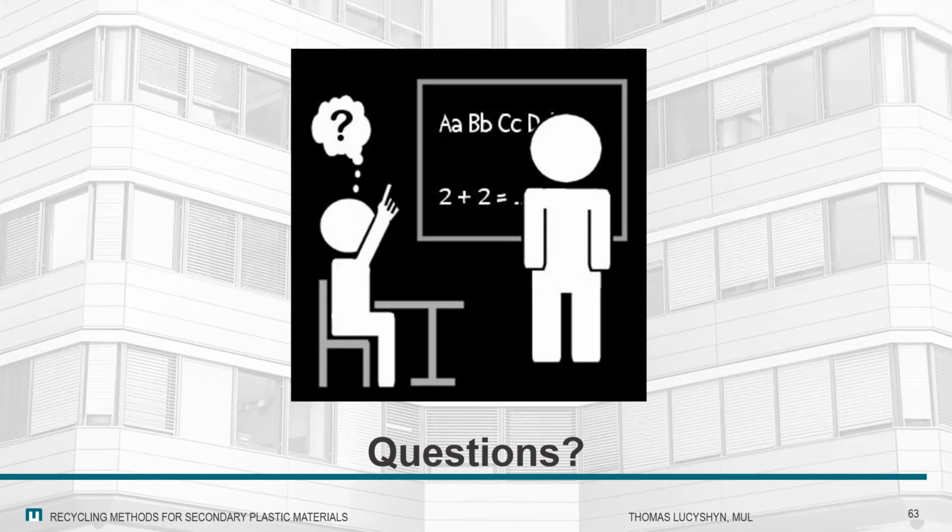All right, this is Sylvie from Dow. Can you hear me? Yes. We can. Hello. I just started to type an answer, but I can verbalize it here. There are different ways in which petrochemical companies can participate in the circular economy, we believe. For the first part, and the most obvious one, I'd like to refer to one of the first options on using recycled material that Professor Lucyshyn was mentioning. One of the approaches to enable the use of recycled materials that are sometimes a little bit contaminated or degraded is to use additives. Antioxidants, but also impact modifiers, for example, which are then often virgin impact modifiers produced by the petrochemical industry. The same story goes for compatibilizers.